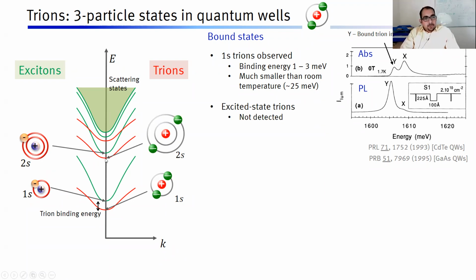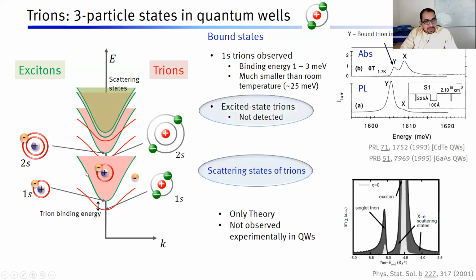Now, what do we expect more? We expect that corresponding to these excited states of excitons, there should be another trion, because you can add an extra electron in this exciton state. So there should be another trion, but these have never been detected in any of the quantum well systems before this work. Similarly, you expect that there should be scattering states of trions, similar to the scattering states of excitons. So these scattering states of trions should start appearing from the exciton's energy, something like this. But these scattering states of trions have been theoretically predicted so far in the spectra, but they have never been observed experimentally in quantum wells.